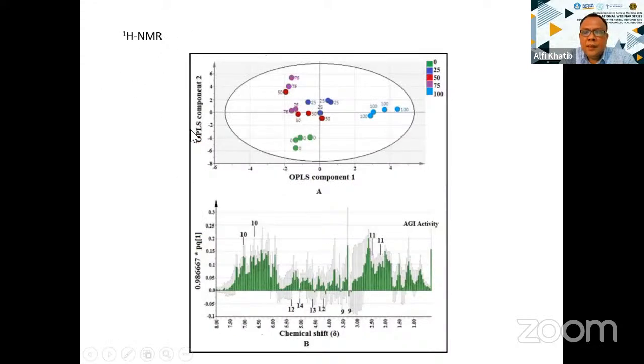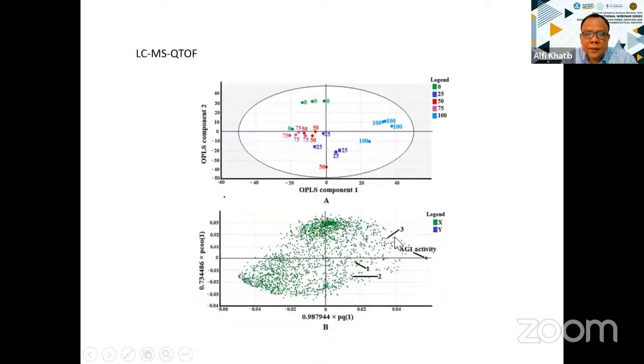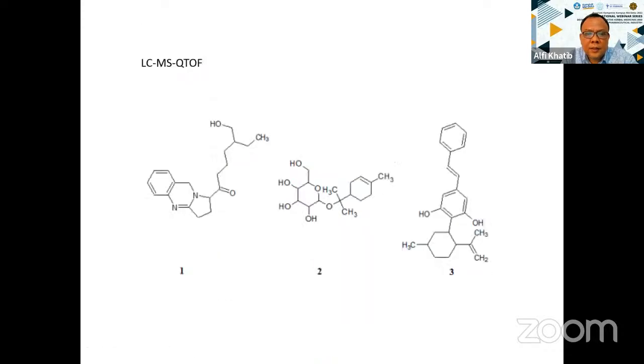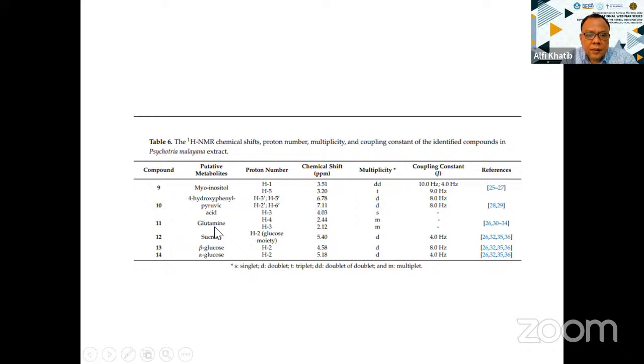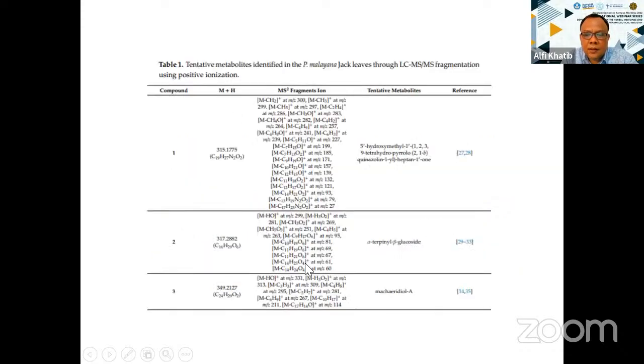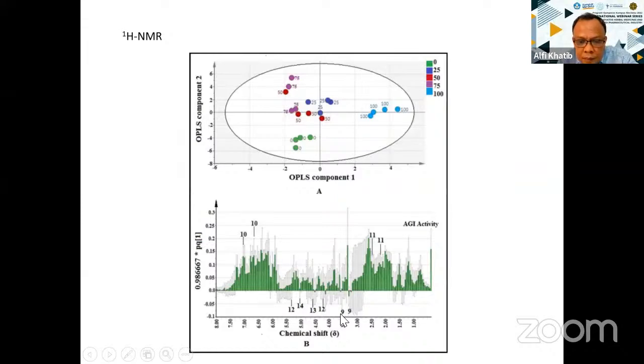And then also NMR, the same case. So you also have the score plot, you have the loading plot, and any compound which is on the same side as the AGI activity means that compound is correlated to the activity, meaning positive correlation to the bioactivity. In this case you have compound 10 and compound 11. We already know these 10 and 11 from last time. This one is the hydroxyphenylpyruvic acid. Another one is the glutamine. Others like inositol or sucrose or glucose have no relation to the activity, because their error bar here is too big, so there is no relation.